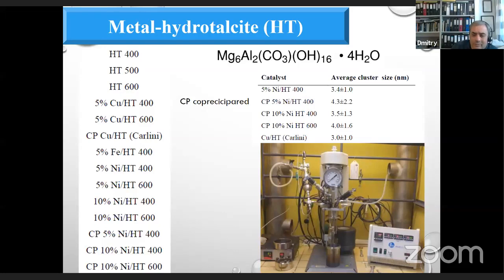Then we identified that hydrotalcite is a promising material. I mentioned it already before. We started to work more on that, and then we were making hydrotalcite. HT stands here for hydrotalcite, and 400, 500, and 600 refers to the calcination temperature. Then we were also making a different type of catalysts based on hydrotalcites, depositing metals on hydrotalcites, or making the catalyst simultaneously using the so-called co-precipitation technique. I think I have a typo in an arrow on the slide. So co-precipitating the metal together with the precursors for magnesia and alumina.